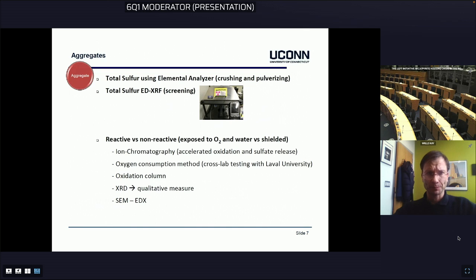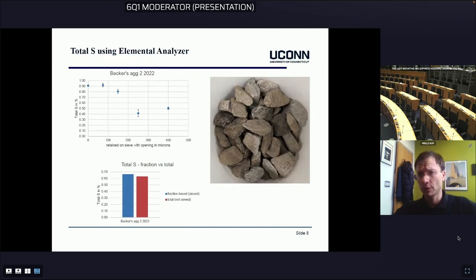Next slide. So here's an example from the method I mentioned just before, using the elemental analyzer. This is the type of material in a preliminary study from the Becker's quarry, where we have crushed it and pulverized it and then measured the total sulfur. We have also sifted it into different fractions and then measured the total sulfur, and you see in the diagram it ranged, in terms of the fraction, from 0.9% total sulfur to about 0.4, but on average it is about 0.6% total sulfur in the aggregate.